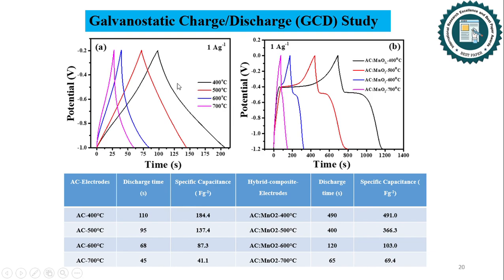Activated AC electrodes displayed distinct triangular profiles characteristic of EDLC with discharge times of approximately 110 seconds for AC 400 degrees centigrade, yielding specific capacitance values of 184.4 farad per gram, whereas hybrid composite electrodes exhibited a bending nature resembling pseudocapacitive behavior attributed to internal oxidation reduction reactions in MnO2, with discharge times for AC MnO2 400 degrees centigrade of 490 seconds, resulting in specific values of 491 farad per gram. Now, let's see the specific retention.